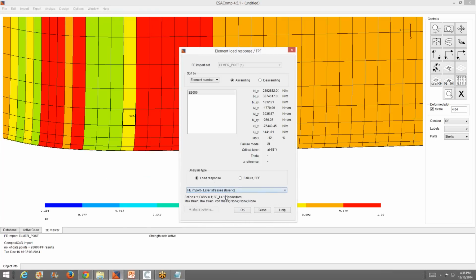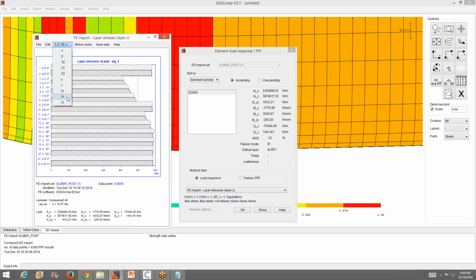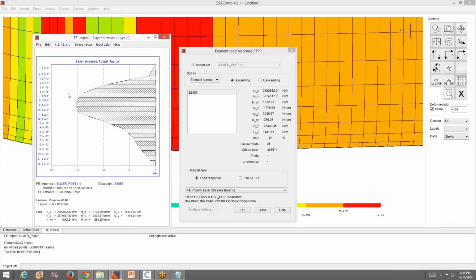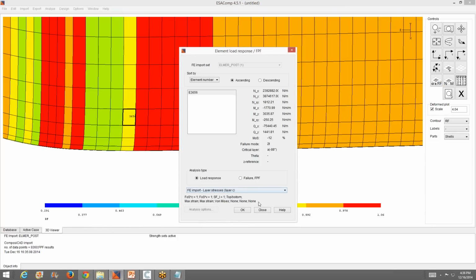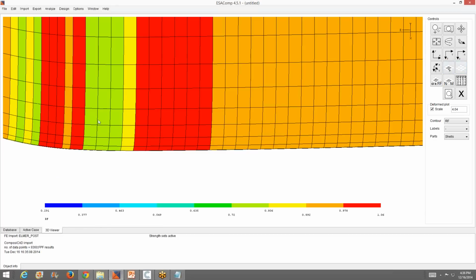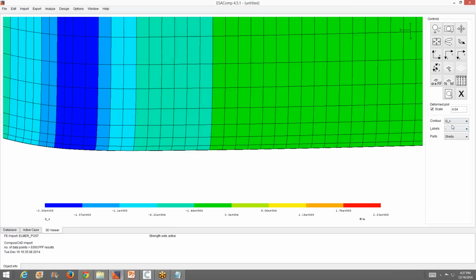But I will take now the stresses, and more specifically I will take the out-of-plane shear stress. So it's moderate in this region, 15 megapascals. Let's study the neighbors, or better, actually, there's a better thing to look at: the result item QX. It indicates out-of-plane stress resultant. So previously I showed you the out-of-plane stress distribution. This QX is like one item that shows the resultant of all the layers.